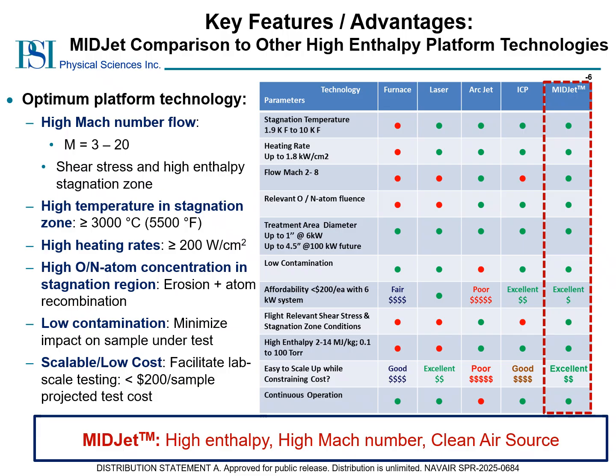The midjet platform stands alone when considering these attributes, along with the additional goals of minimizing both testing cost and test article contamination from the platform technology. The midjet-based platform reduces the cost of testing due to the relatively low cost of the infrastructure needed to operate the facility compared to the hundreds of kilowatts to multi-megawatt inductively coupled plasma torch and arc jet facilities. The 6 kilowatt Hypersonic Materials Testbed provides a clean and accurate test environment at substantially lower cost than these other platforms, with a projected cost of less than $200 per test sample at moderate test volumes.